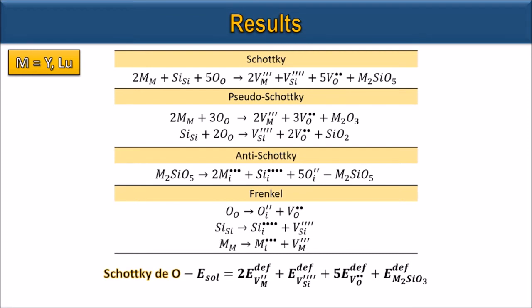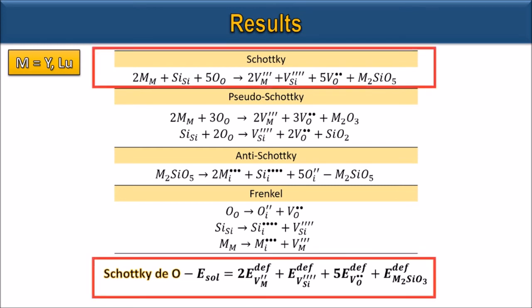This slide shows the types of defects calculated in the structures. These defects involve only vacancies and interstitial ions of one of the three types of ions that form the structure. In these calculations, the defects are far enough apart in the structures to not interact with each other, which are called unbound defects. The energy cost for all possible individual point defects, vacancies and interstitials, were obtained, and the energy to produce the unbound intrinsic defects was estimated considering the reactions in this table.